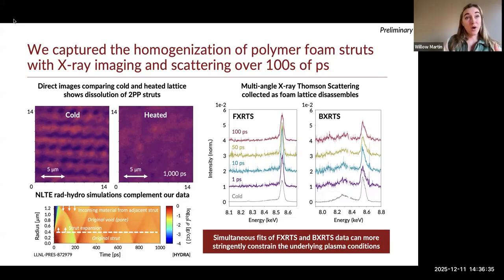So if you were to try to model the heating at short time scales, you would need something like PIC. But if you are interested in evolution out at longer time scales, for these short pulse lasers you can assume rapid energy deposition in a short time early on, and then just use that as an initial condition for the subsequent evolution of your target. So in these hydrodynamic simulations, I initialize the electron population with some elevated temperature and leave the ions cold, and let the two populations evolve independently.